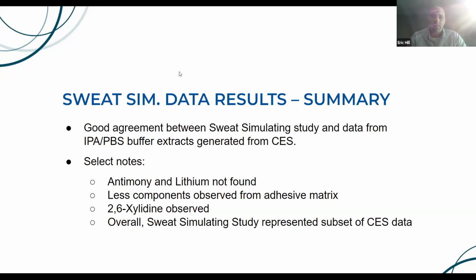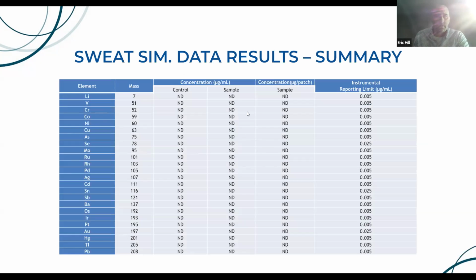Essentially, the sweat simulation study was a subset of the controlled extraction study data, again, which is what we would expect. The controlled extraction study is designed specifically to be worst case, whereas the sweat simulation study is really mimicking worst case use, but not necessarily worst case extraction. And so we expect that to be a subset, and it was. We did not see the antimony and lithium. We also saw fewer components, as I mentioned, from that adhesive matrix. The 2,6-xylidine was observed, and overall, again, it was a subset. We look at the inorganic analysis. Again, the sweat simulation study data was very clean. We did not see the lithium or the antimony, or anything else.